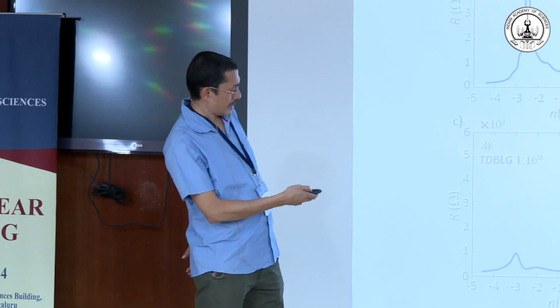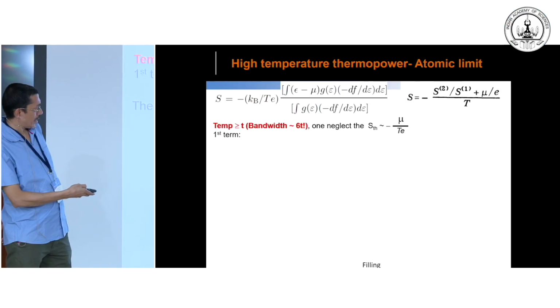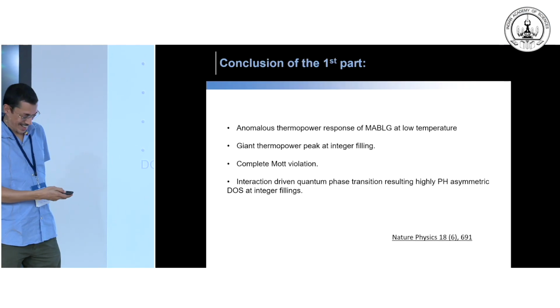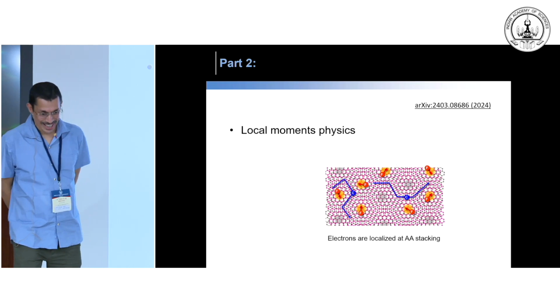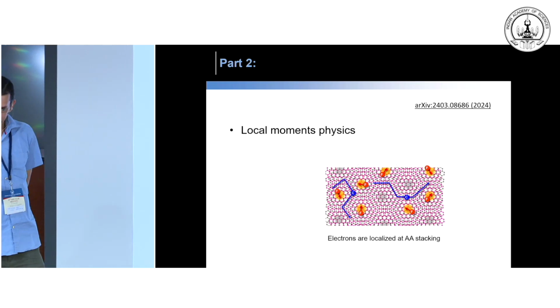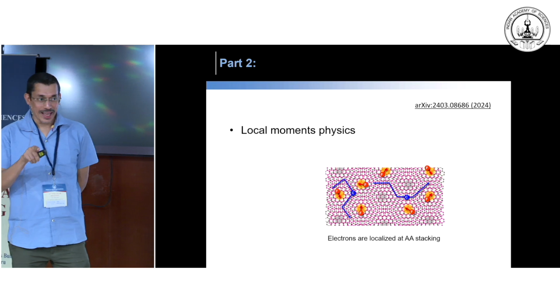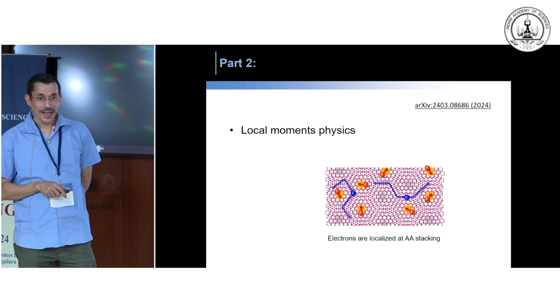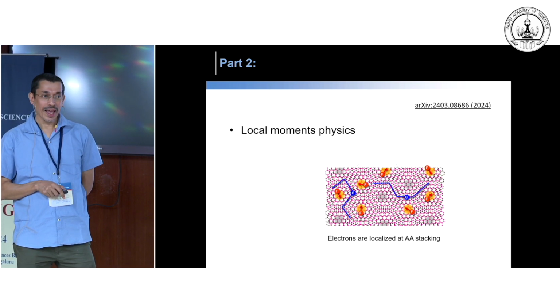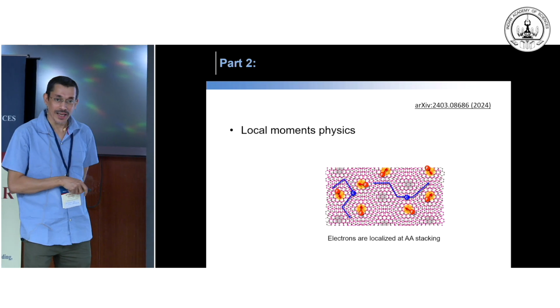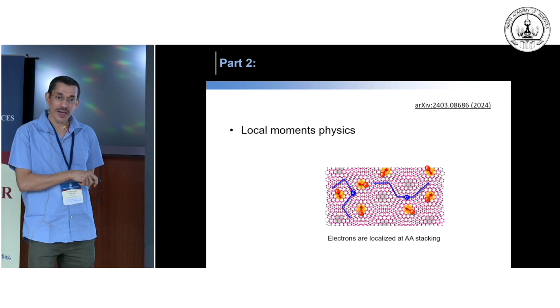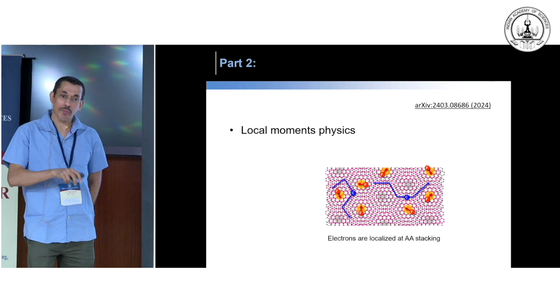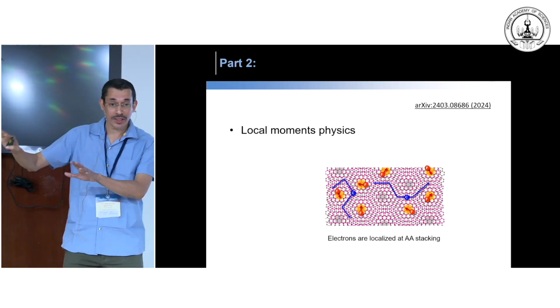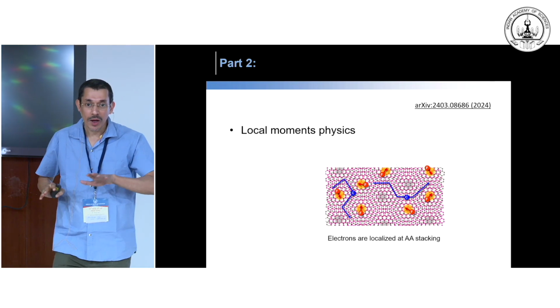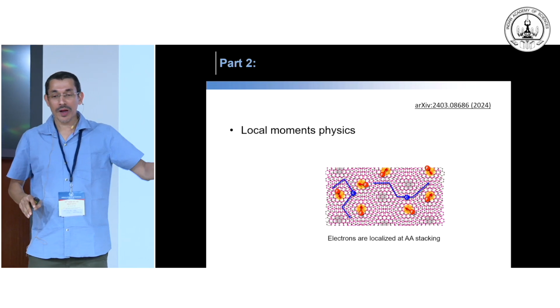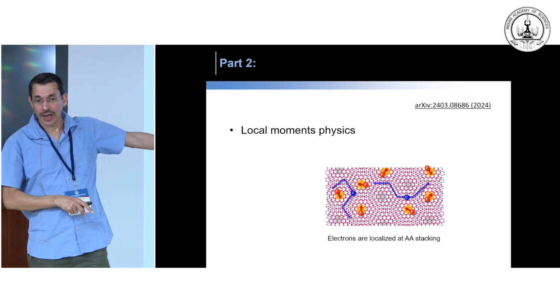This is my second part. So that's one way I would understand high Seebeck coefficient. If you remember the famous work of Mildred Dresselhaus, which suggested nanowires giving very high Seebeck coefficient. So you essentially have a network of nanowires in the bilayer system. Absolutely. So that's quite interesting. Yeah. So in fact, the system has both characters. You have localized electrons somehow and also some itinerant electrons.